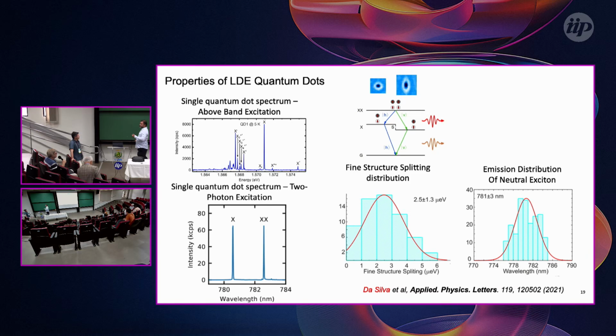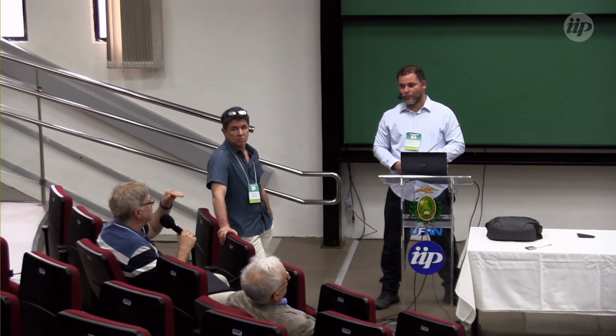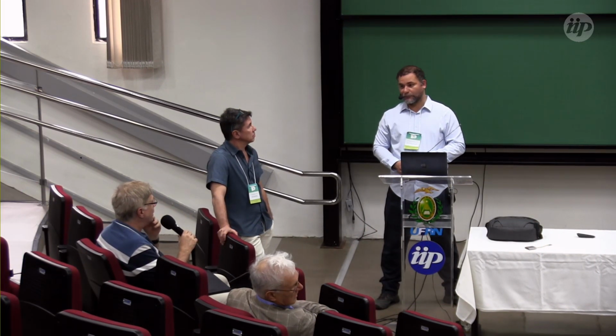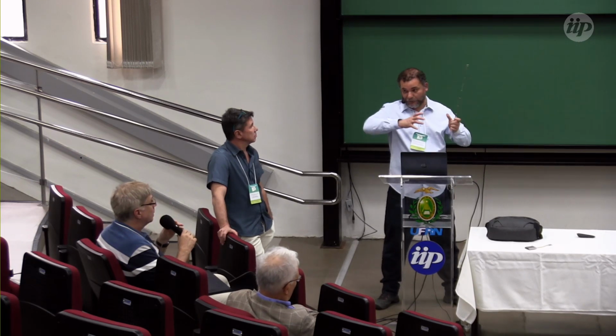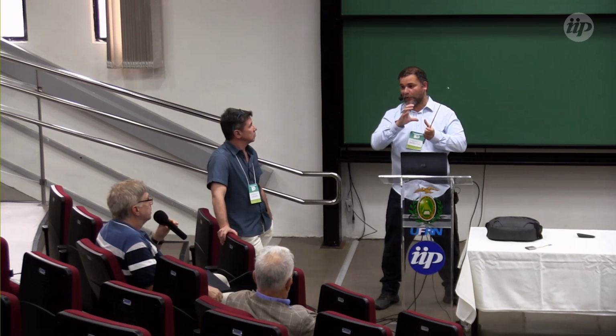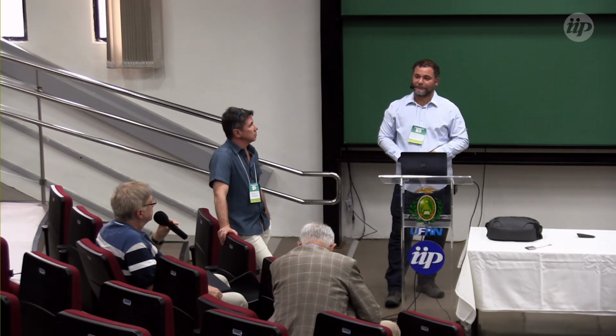But for indium arsenide quantum dots, you have several things that can influence the fine structure splitting, like strain, the indium concentration, but size. With strain free, the size will change. I thought the size will only change the position, not the fine structure. No, the symmetry, because it's the symmetry of the confined potential, and this is influencing the fine structure splitting.